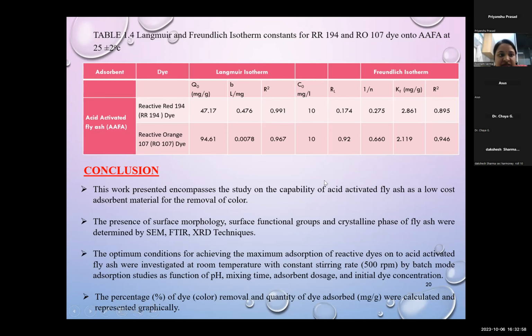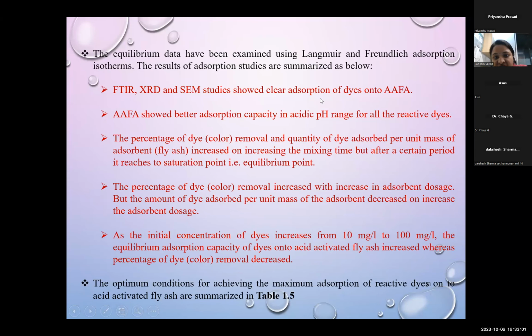The conclusion is that FTIR shows clear adsorption of dyes onto AAFA. AAFA showed better adsorption capacity in the acidic pH range for all the reactive dyes. The percentage of dye removal and quantity of dye adsorbed per unit mass of adsorbent increased with increasing mixing time, but after a certain period it reaches the saturation or equilibrium point. The percentage of dye removal increased with increase in adsorbent dose, but the amount of dye adsorbed per unit mass of adsorbent decreased on increasing the adsorbent dose.